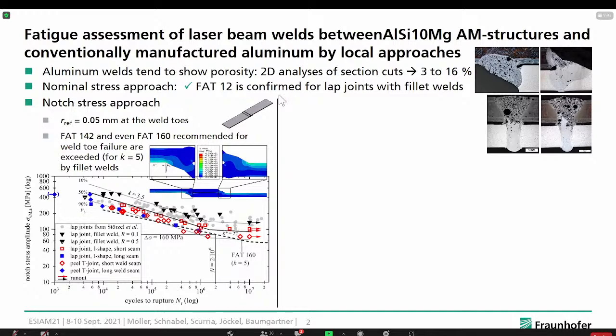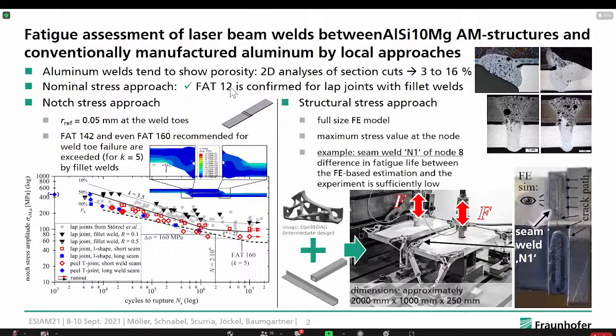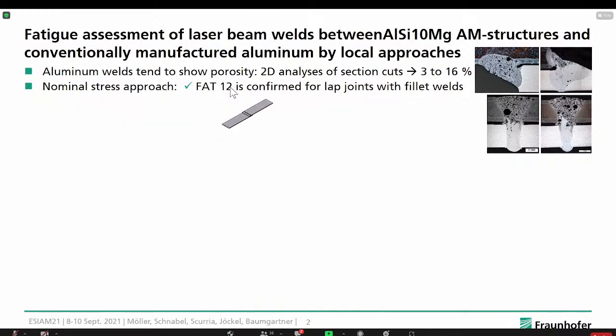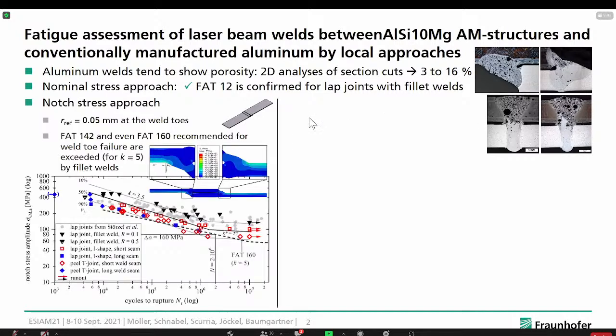What we found is that for these fillet welds, the recommendations fit quite well. For this case, it's FAT 12, which has to be applied. We have also seen that the porosity in this weld increases, especially in the area where we have the additively manufactured material. These are two main points coming from the experimental work, and then we started to try to develop local methods for assessing these joints.